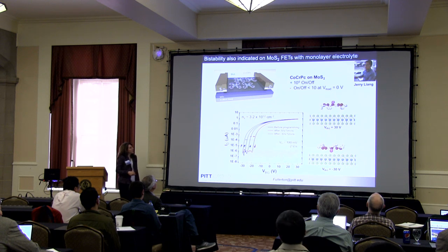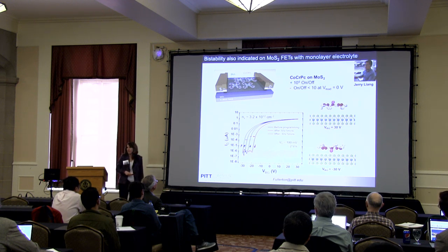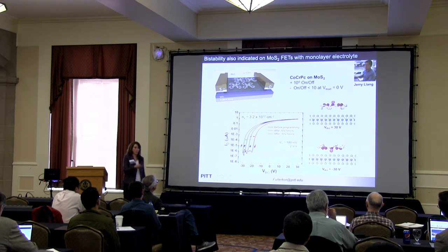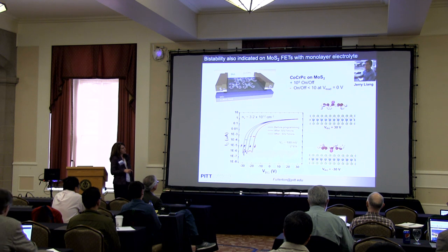We also investigated the program-erase voltages, because there's some threshold voltage you have to apply in order to get this thing to switch. So he started way up here and he walked down until he couldn't switch anymore. And he noticed this threshold voltage, at least backgated, is around 12 volts. I'm not really sure how to predict what this will be when we top gate it, but that's what we're actively working on now, getting a top gate down on that boron nitride dielectric.